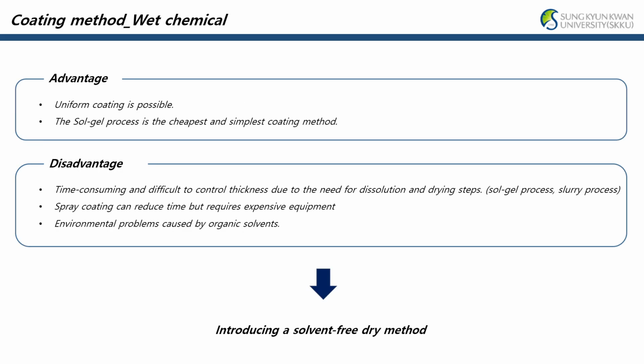Wet chemical enables uniform coating, and the sol-gel process I just introduced has the advantage of being the simplest coating method. However, dissolution and drying steps are required, which are time-consuming and quite difficult to control the thickness. Spray coating can shorten the time, but it requires expensive equipment. In addition, all wet chemical coating have environmental problems due to organic solvents, so it can be solved to introduce a dry method that enables uniform coating without using a solvent.